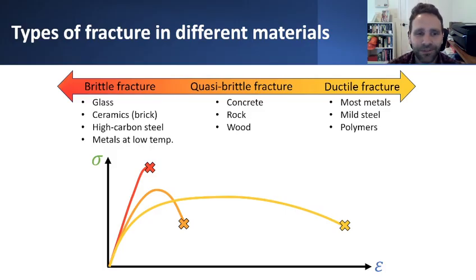And also, this is true of other types of metals if they're at relatively low temperature. And for most of these materials, what you'll see in a stress strain curve, if you're maybe doing a uniaxial tension test on some simple tensile specimen, is that you could load up the material up to some critical threshold, and then instantaneously or nearly instantaneously, you'll just have an instantaneous loss of load carrying capacity, indicating that the material undergoes practically no plasticity or any kind of plastic deformations. It just fails.